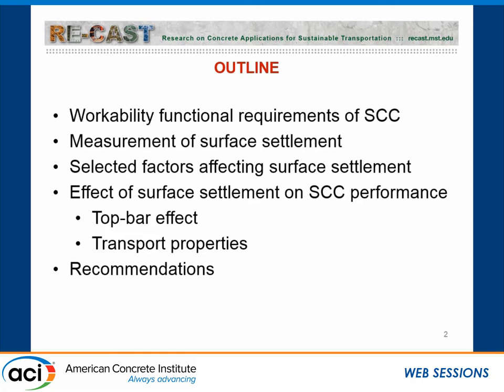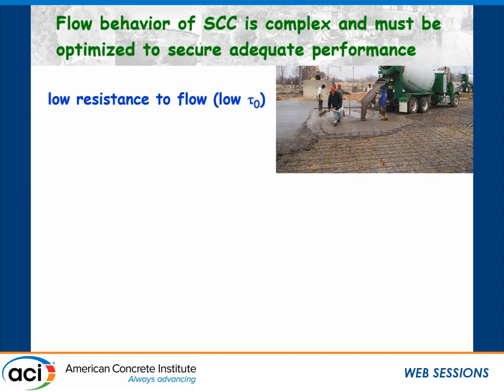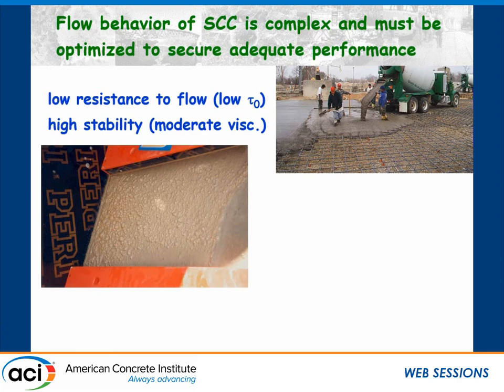As you know, SCC has to have a very high slump flow, i.e. low yield stress, which is a minimum resistance to shear to induce flowability. So we have to design a concrete with very low yield stress, where bleeding becomes an issue, segregation becomes an issue, and settlement. So it also has to be highly stable once it's being cast, and that's dynamic segregation resistance, but also after casting until the onset of hardening.